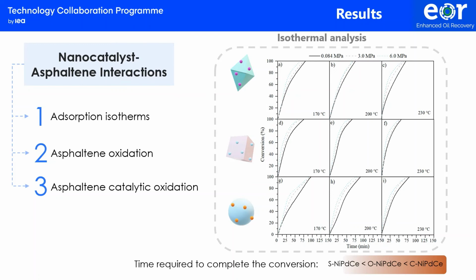The second aspect could be related to the presence of nickel and palladium leading to faster activation of ceria nanoparticles, which may facilitate the migration of the oxygen vacancies from the bulk to the surface of the ceria nanoparticles.